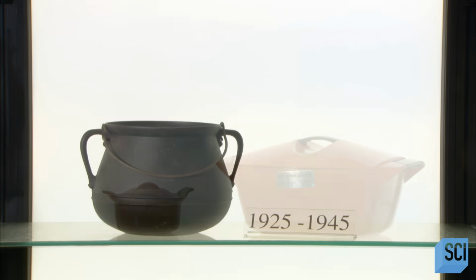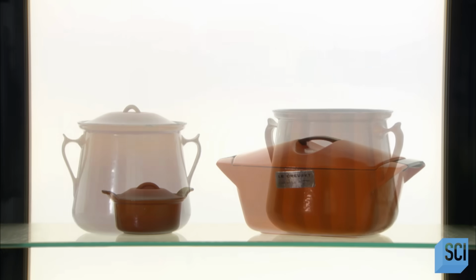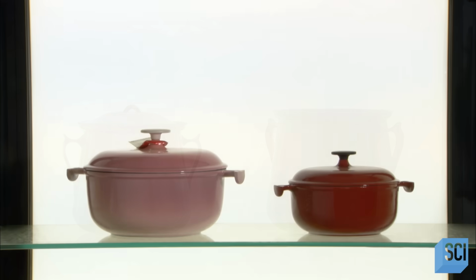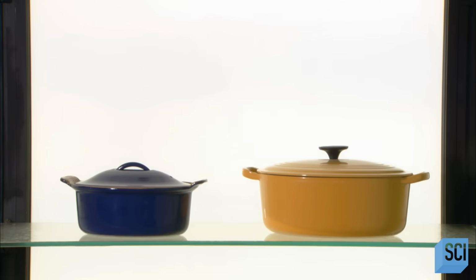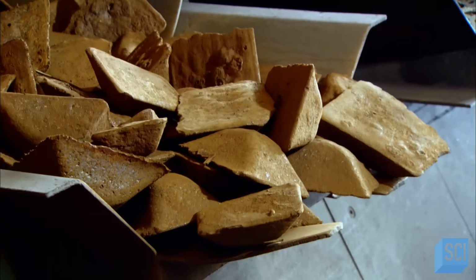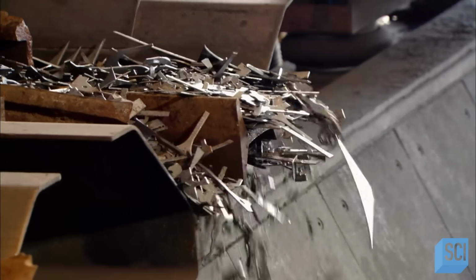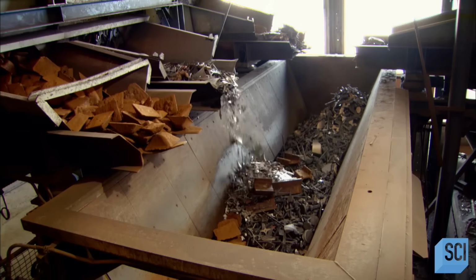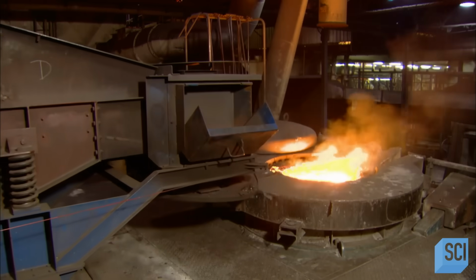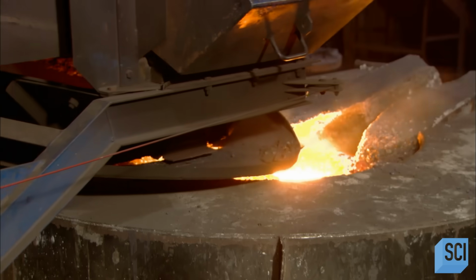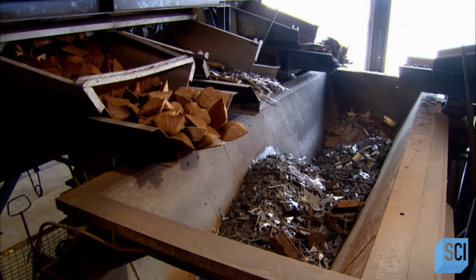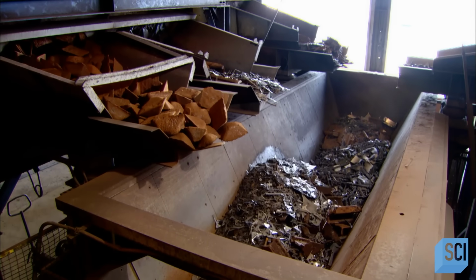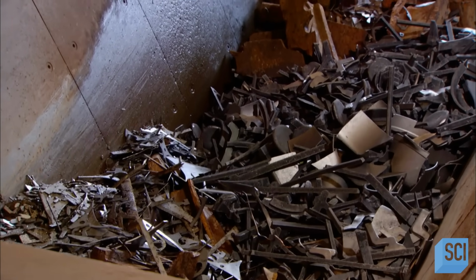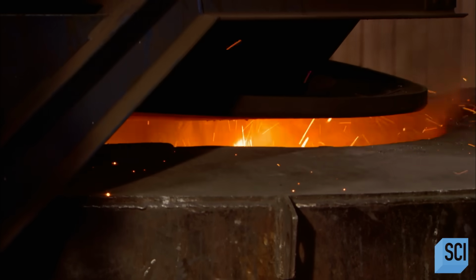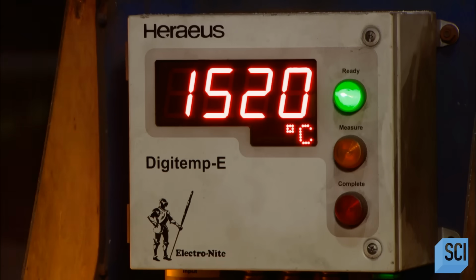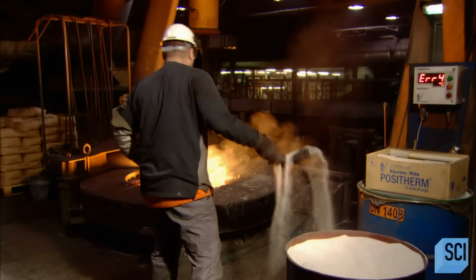Since 1925, this French company has been producing enameled cast iron cookware. Its high-end products are renowned for their thin walls, which makes it the most lightweight cast iron cookware available. The secret? The mineral levels in the iron recipe. At the foundry, they begin with pig iron, which has a high carbon content. Then they melt in a calculated amount of steel to further boost the carbon level. The melting oven heats the metals to 1520 degrees Celsius, liquefying them in just 45 minutes.